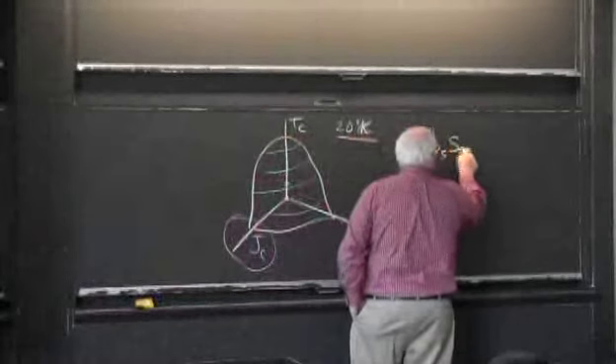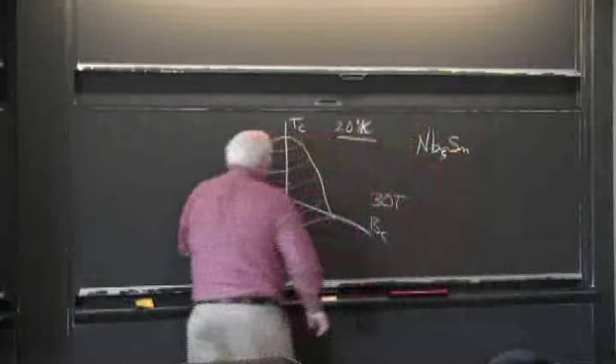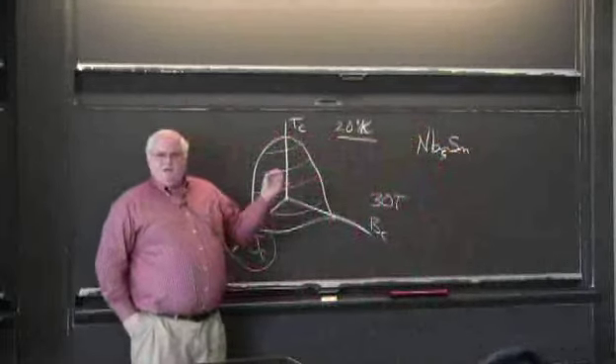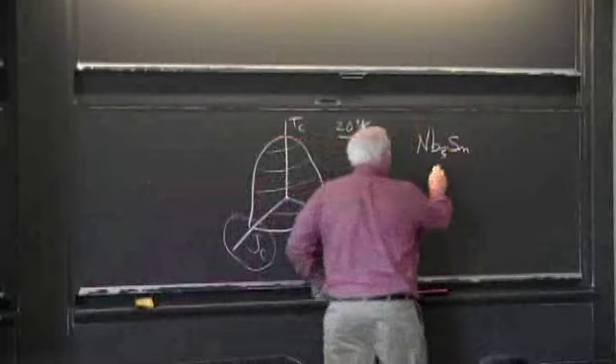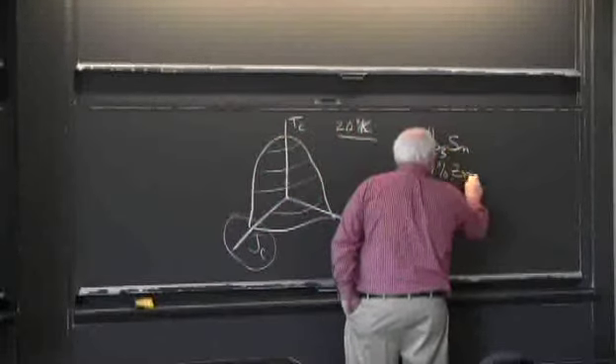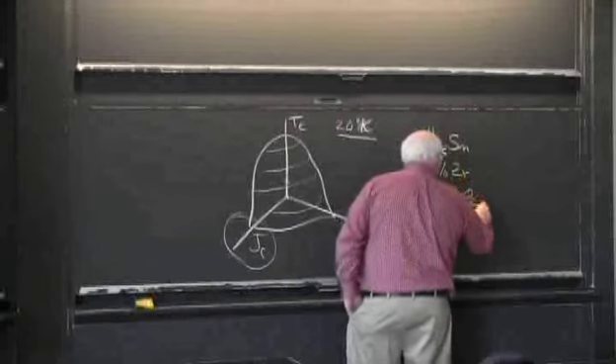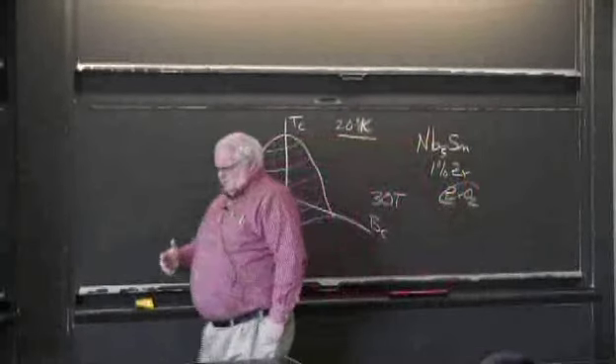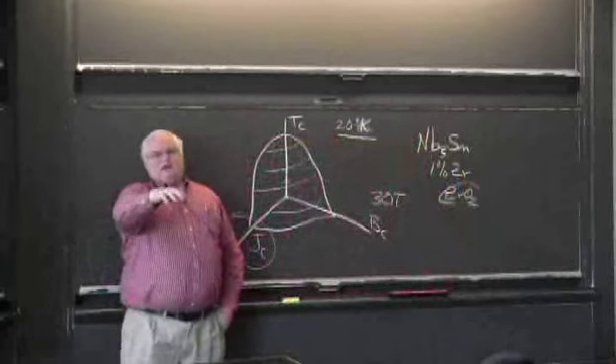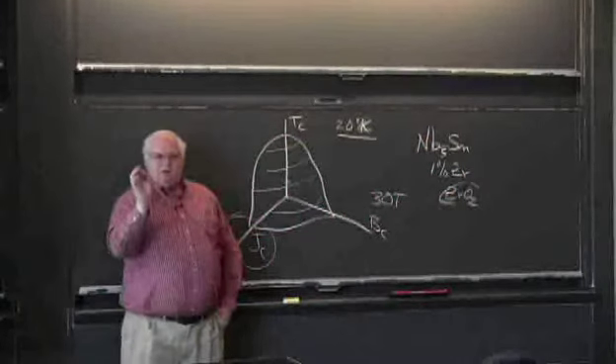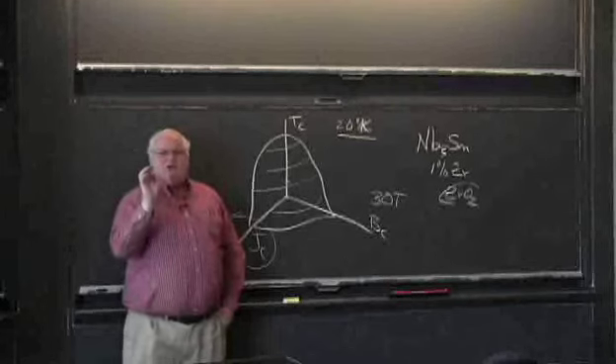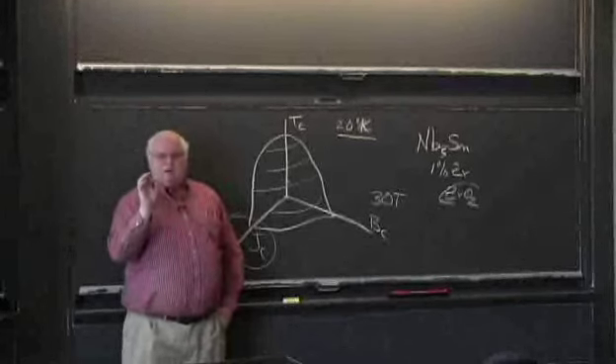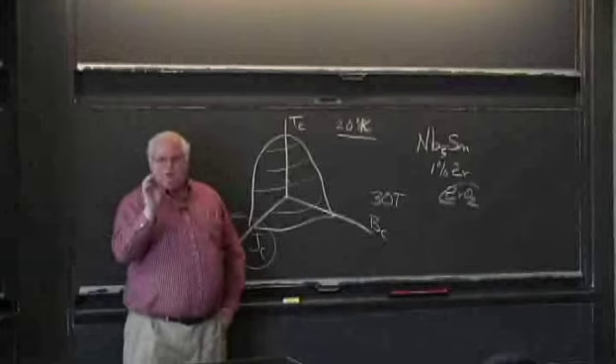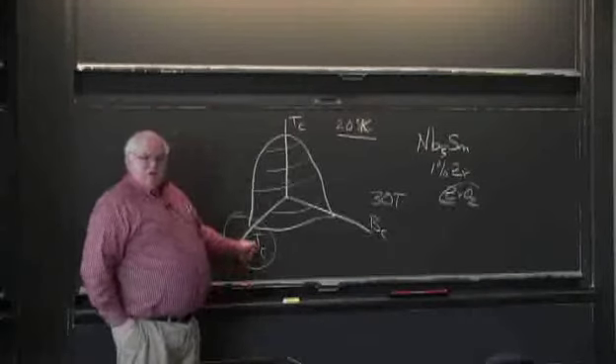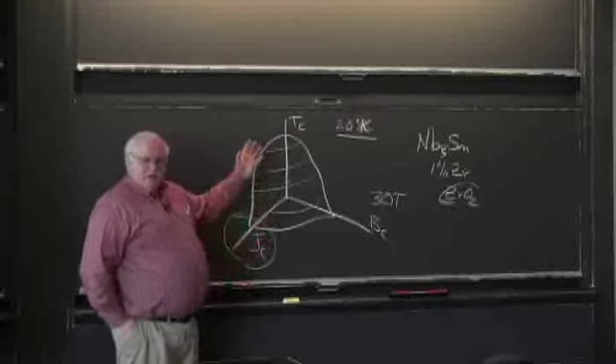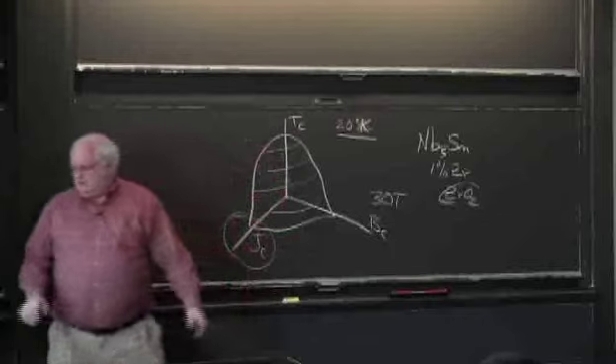This is not what I was going to lecture on today. And niobium-tin, Nb3Sn,, they found that if they put zirconium in there, 1% zirconium, they could internally oxidize it and form zirconium oxide precipitates on a nanometer scale. I can use that term today. We didn't call them nanometer, but basically they had to be like 100 nanometers apart. These were like 20 or 30 nanometer precipitates, because that's what gave you a good critical field. If you had really pure stuff, you wouldn't get decent properties.